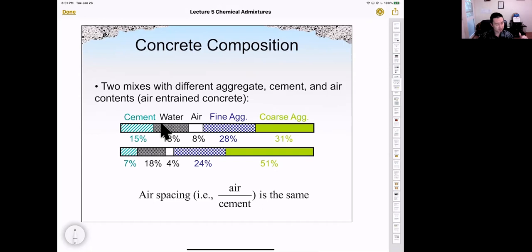Now here we show two mixes with different percentages of aggregate, cement, and air. We care more about the air spacing, which is the ratio of the amount of air to the amount of cement. That ratio is more important compared to the air percent by itself. This concrete has 8% air and the other one has 4% air, but air spacing, the ratio of air over cement, is more correlated to the durability against freeze-thaw damage.